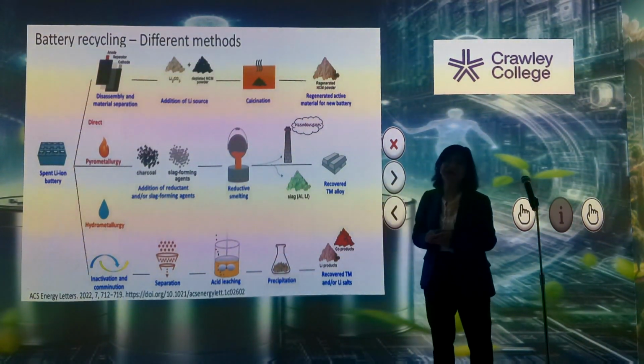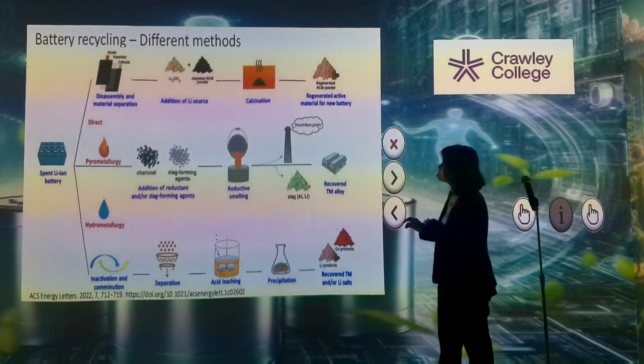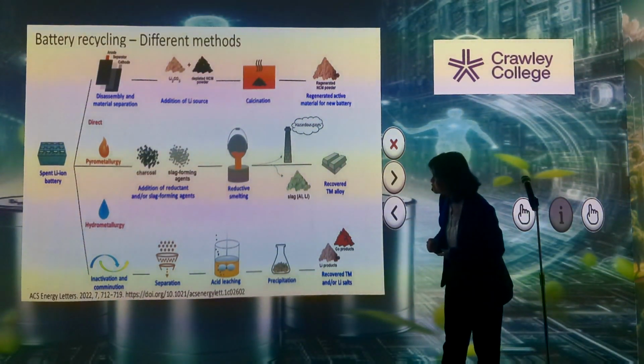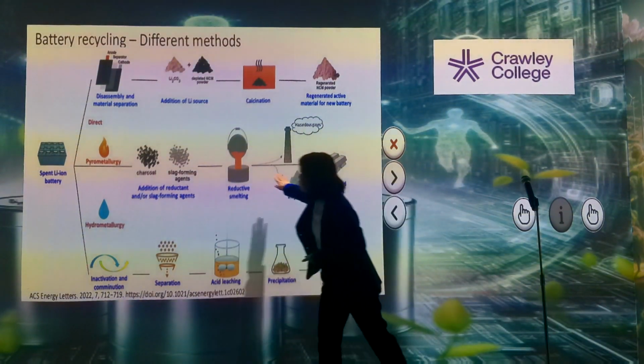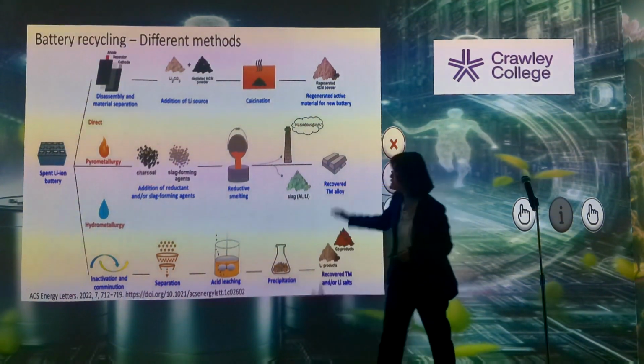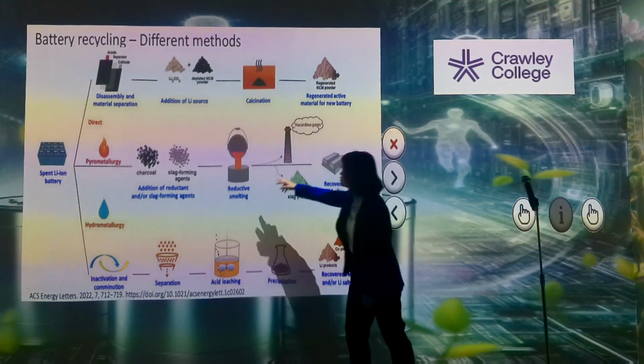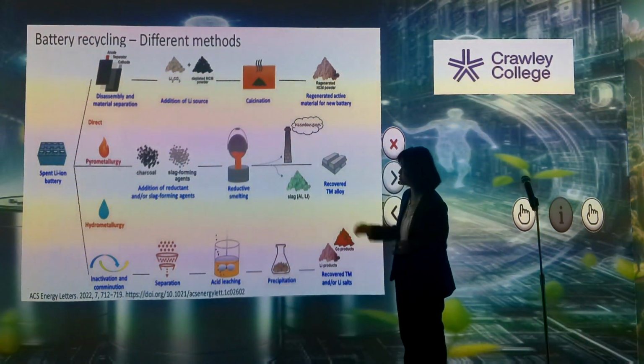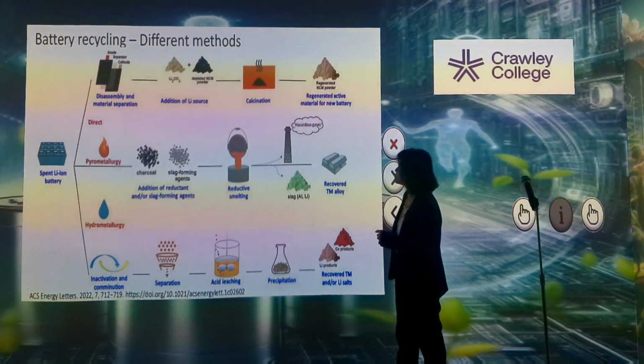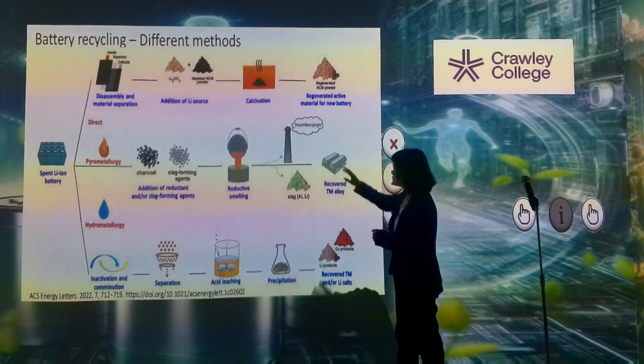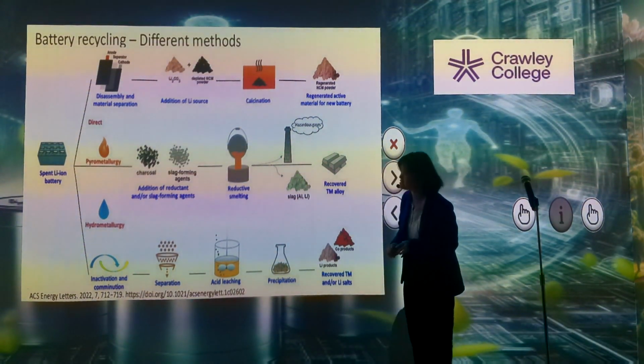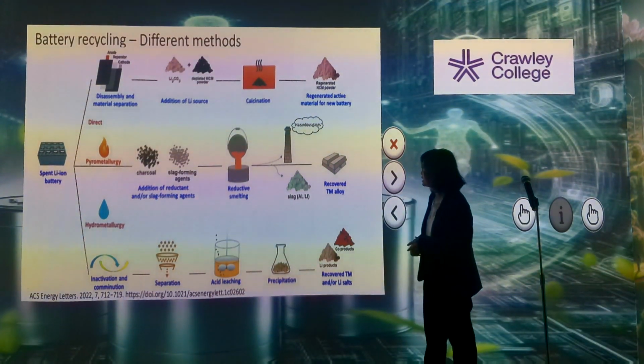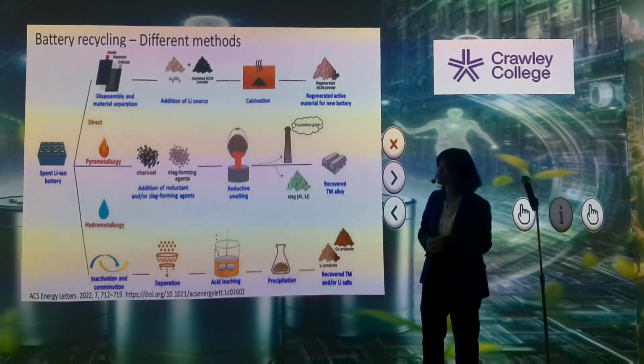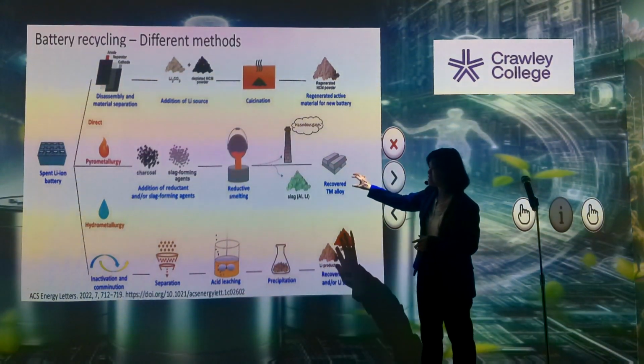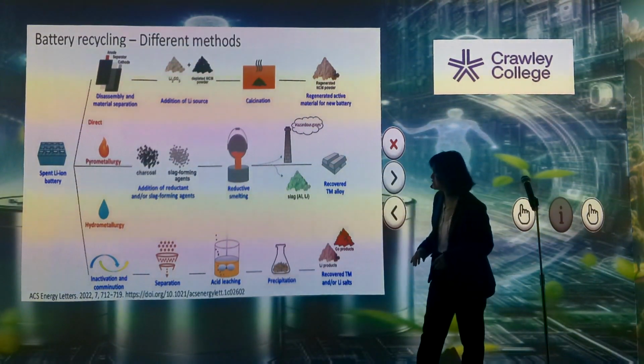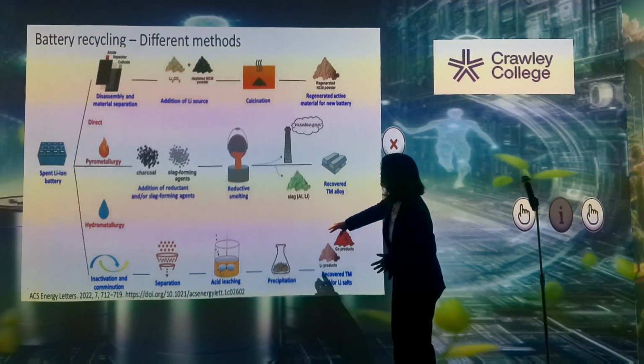And so currently there are a few different methods trying to recycle the battery materials. One of them, let me start from this one. This is the pyrometallurgy method, where you basically burn them at a very high temperature, and then you apply the reductive smelting process, trying to put some reductive agent. This typically happens at a very high temperature, could be up to 1,400 degrees C. During that process, because it's burning, you release a lot of hazardous gases, and that high temperature is very energy intensive. So you can recover some transition metal alloys from that process, but as I say, it's a very energy intensive process. Currently in China and also in Asian countries, this is the method that is commonly used.